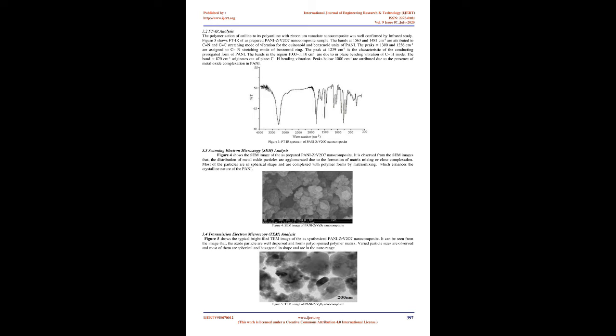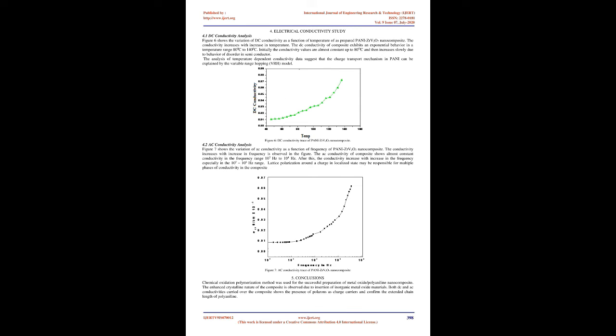3.2 FTIR analysis. The polymerization of aniline to polyaniline with zirconium vanadate nanocomposite was well confirmed by infrared study. Figure 3 shows FTIR of the prepared PANI/ZrV2O7 nanocomposite sample. The bands at 1563 and 1481 cm⁻¹ are attributed to C=N and C=C stretching mode of vibration for the quinonoid and benzenoid units of PANI. The peaks at 1300 and 1236 cm⁻¹ are assigned to C-N stretching mode of benzenoid ring. The peak at 1239 cm⁻¹ is the characteristic of the conducting protonated form of PANI.